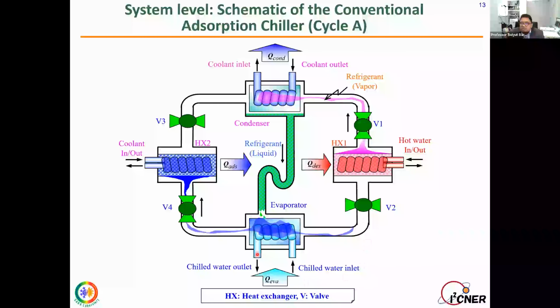The system is under vacuum condition. So the pressure is 1/100th of the atmospheric pressure, about 1 kilopascal. At this pressure, water evaporates and goes through valve 4 to our adsorber bed, and adsorption is happening here. Due to the exothermic properties of adsorbent materials, heat is generated in this bed, and we need to cool down the bed. On the other hand, here you can see valve 2 is closed. Instead of cooling water here, we are using hot water. This is our heat source. We can take this heat from solar energy or from waste heat sources, about 80 degrees centigrade. And then we regenerate the water which is inside the heat exchanger.